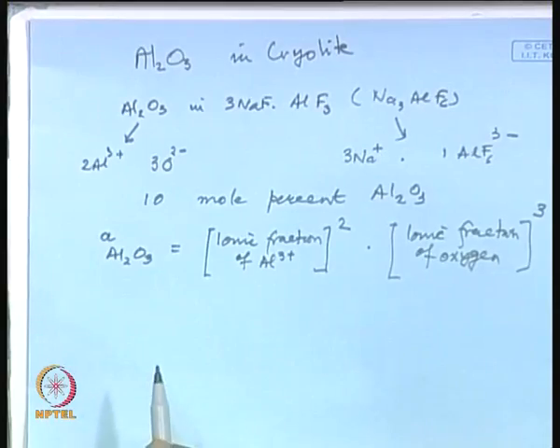Cations can move in the cation sublattice, anions move in the anion sublattice, such that a cation is always surrounded by anions and anion is always surrounded by cations. When we say activity of alumina, we really mean the probability of finding two aluminum atoms in close proximity of 3 oxygen atoms.